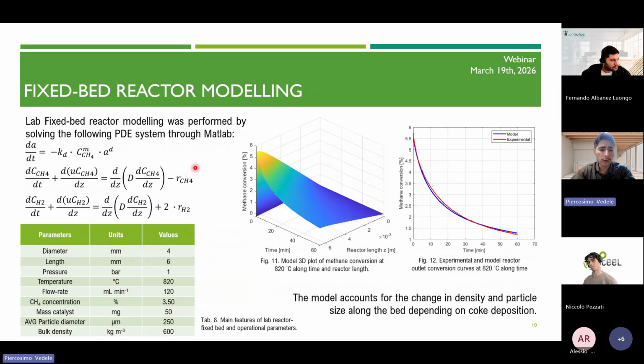These kinds of results were useful for the modeling of our fixed bed reactor. By solving through MATLAB this partial differential equation, we were able to get the profile of the methane conversion all along the time and all along the length of our reactor. Here you can see the main characteristics of the reactor, and from here you can see that our model is able to fit quite well the experimental results that we obtained from our tests conducted at 820 Celsius degrees. Of course, the model takes into account also the change in density and the change in particle size, which is related to